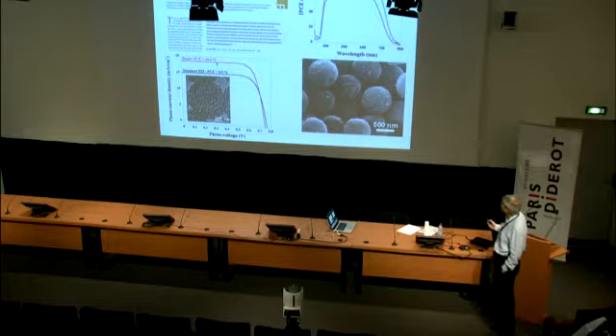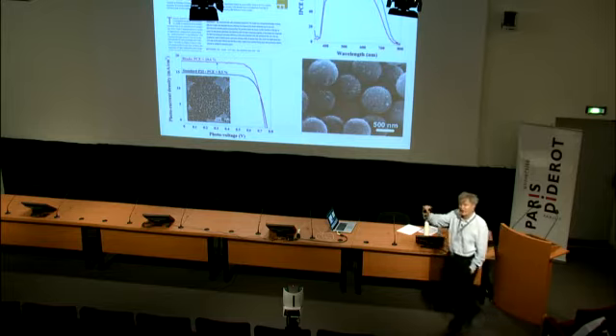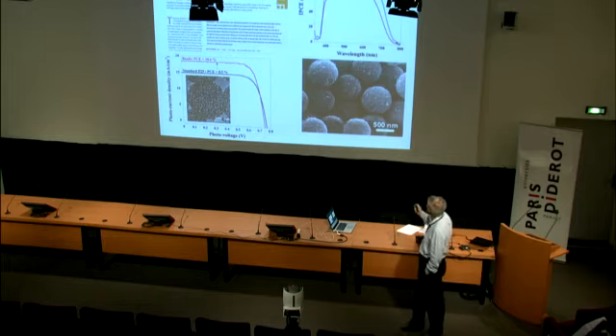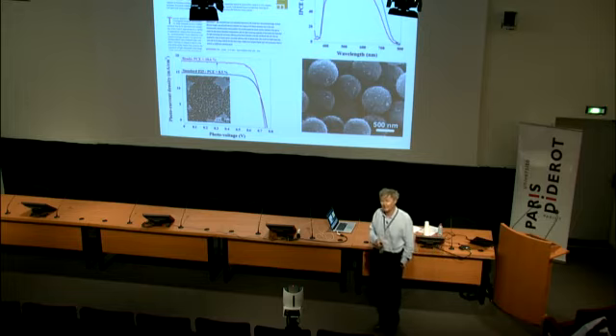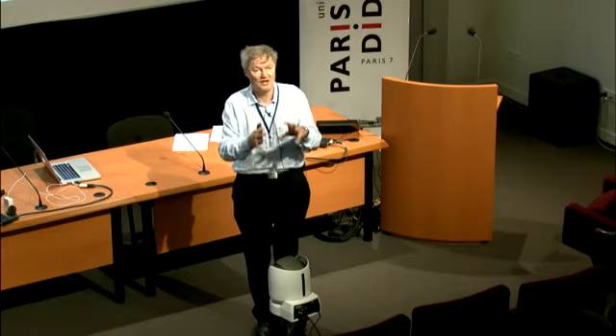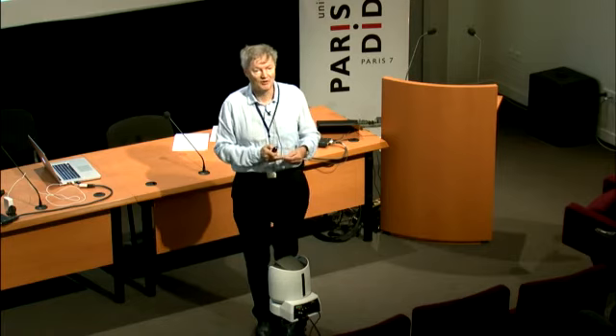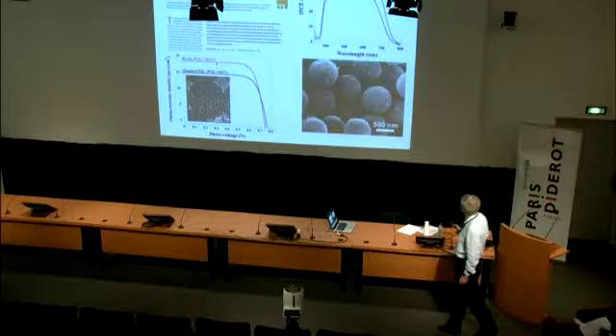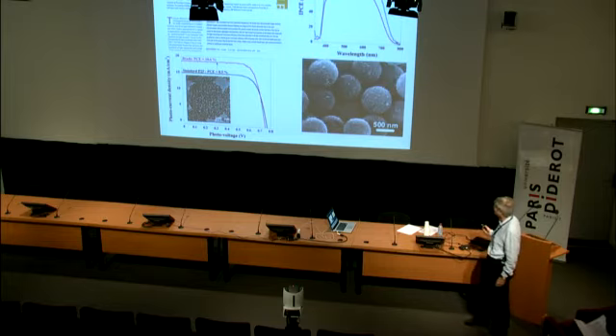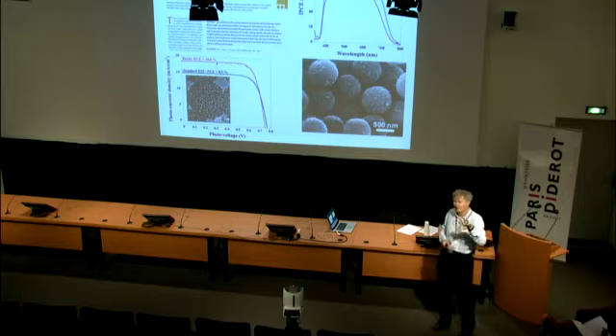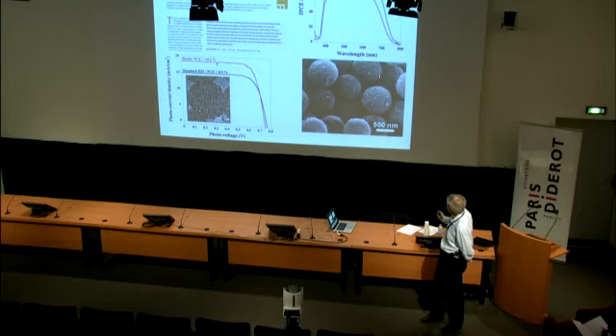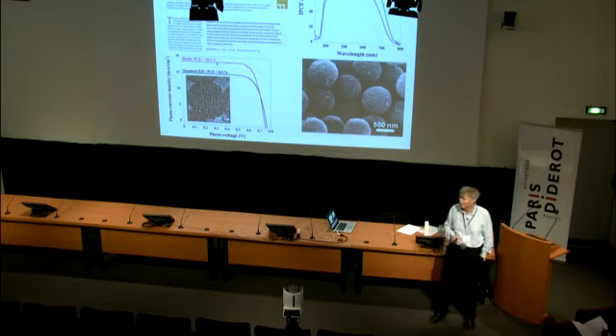power conversion efficiency. It shows you the advantage: beads over P25 get a better light response because the light is contained. When the light hits those particles, if it's within the absorption range, you have nearly 100% conversion of incident photon to electric current. So there is a surge of power coming out of these balls once you hit them with photons. That's good, but that's not the only advantage. You have light scattering, that multiple light scattering contains the light in the structure when you are in the tailing part of the spectral region where the sensitizer has a poor light absorption.